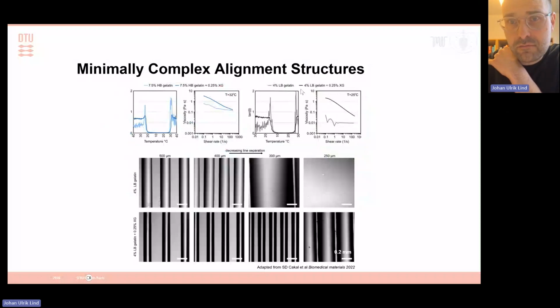And to get better fidelity, we added a little bit of xanthan gum, so a viscosity modifier that increases the viscosity of the gelatin, commonly used. And you can see here, when you add this to the soft material, then you get more well-defined lines that you can space closer before they start merging. So in this case, we have merging quite rapidly if you don't add the xanthan gum. So this is just a small trick.